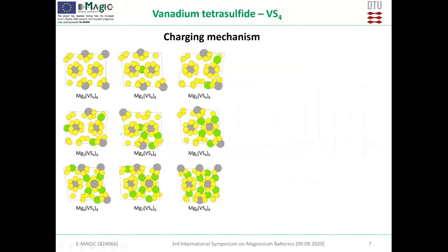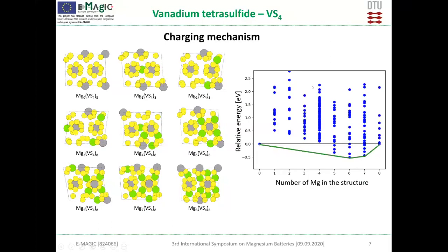And then if we look at the energies, I should mention here that each of the dots, green and blue dot, represents one structure and one energy that we got. In fact, we are interested just in the lowest energies, so the lowest dots. If we look closely, we can see that for the structures with 1 magnesium to 5 magnesium, we have energies that are indicating not stability of the phase. That means we have a phase that has, for example, 3 magnesium in the structure, which will decompose, disproportionate to the empty one and the one with 6 magnesium.